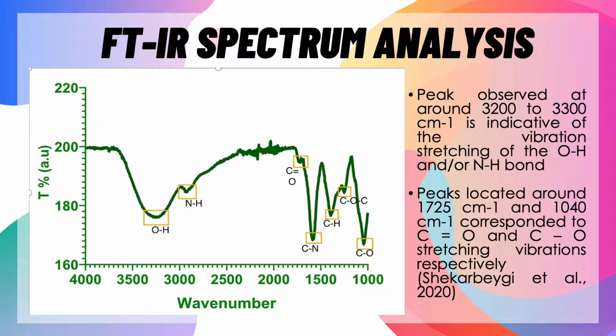The peak at 2920 would be related to vibrations of CH stretching. Again, I reiterate, the presence of these functional oxygenated groups, as you can see. All the oxygenated groups will give rise to the soluble properties of the carbon dots. So all FTIR features contribute to the outstanding solubility of the CPH CDs, so it'll be very useful for further modifications and biological applications.